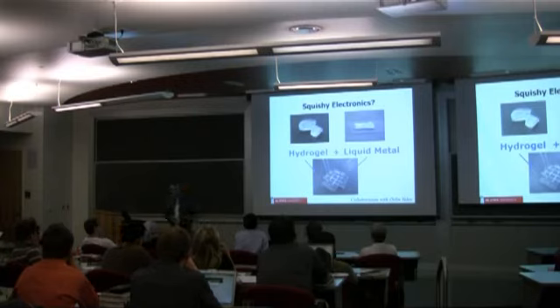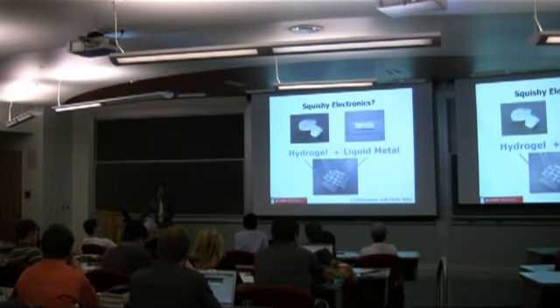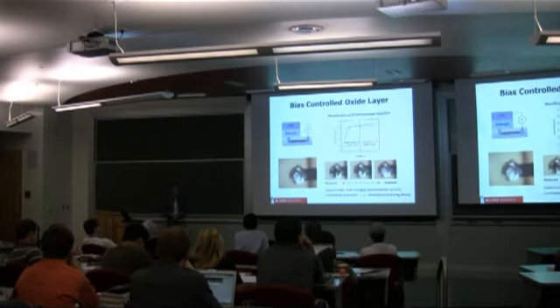But he was making them not so interesting by slapping on rigid electrodes like copper and ITO. And so we very naively thought, well, if we take the liquid metal and combine it with the gel, we're going to have something that's entirely soft and squishy and aqueous-based and uses ions, and it's going to have a bunch of interesting properties. But something happened that we didn't foresee. And that is that at the interface between the metal and the gel, something very interesting happens. And so this is the experiment that I'm going to describe.